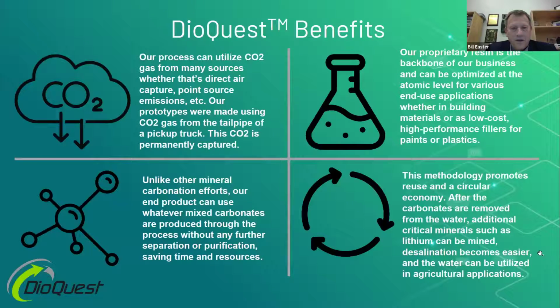And again, we're able to take any CO2 source, could be direct air capture, point source. Even the prototype you saw, we hooked up the carbon dioxide from a pickup truck. And the CO2 is permanently captured. It's almost like a synthetic limestone kind of process. And we're not really concerned, using it as an aggregate, about the purity of it. It can have calcium, magnesium, strontium. It doesn't matter.